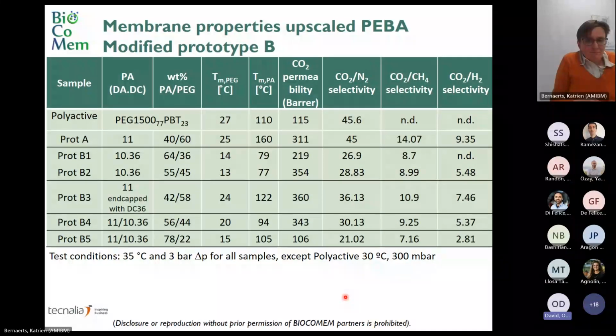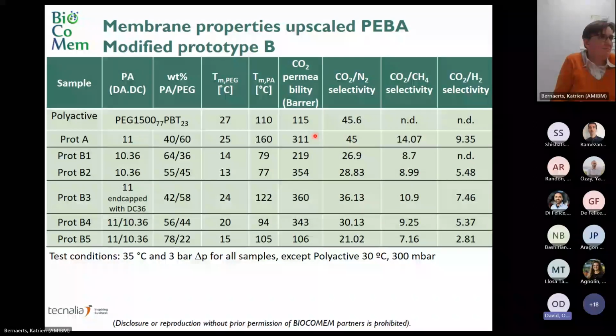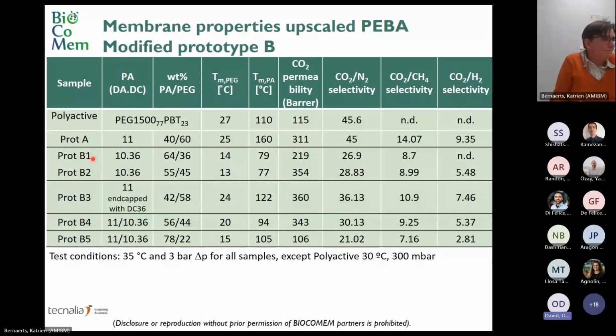And then we have the prototype A, which is our reference bio-based PEBAX with polyamide 11 as the polyamide block. Here we have a higher carbon dioxide permeability, like 3 times higher, at a comparable carbon dioxide to nitrogen selectivity. Then we have this lab scale prototype. I think it is the lab scale, yes. B1 and B2. B1 is the lab scale, B2 is upscaled, but it has a different composition.